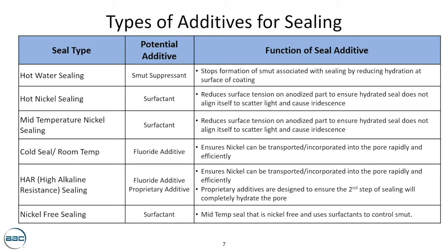So in the case of hot water sealing, as I mentioned before, when you take an anodized part and put it into a hot DI bath of water, after it's in there for more than 3 or 4 minutes, you start getting sealing smut. And smut isn't a bad thing. It indicates that you're actually getting the hydration of the pore, but optically and cosmetically, it doesn't look good.